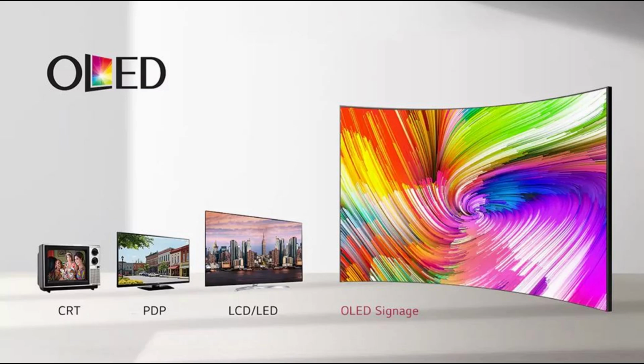Metals such as barium and calcium are often used for the cathode as they have low work functions which promote injection of electrons into the LUMO of the organic layer. Such metals are reactive, so they require a capping layer of aluminium to avoid degradation. Two secondary benefits of the aluminum capping layer include robustness to electrical contacts and the back reflection of emitted light out to the transparent ITO layer.